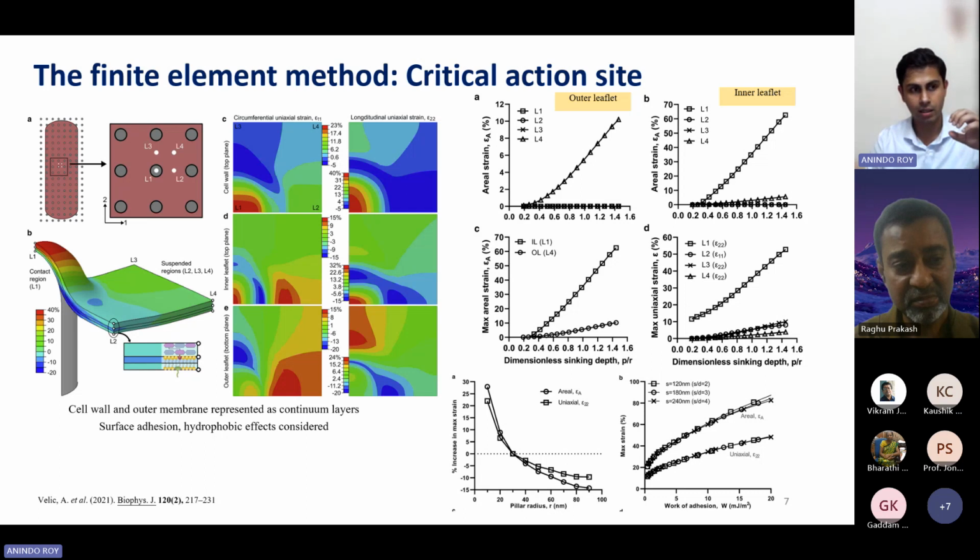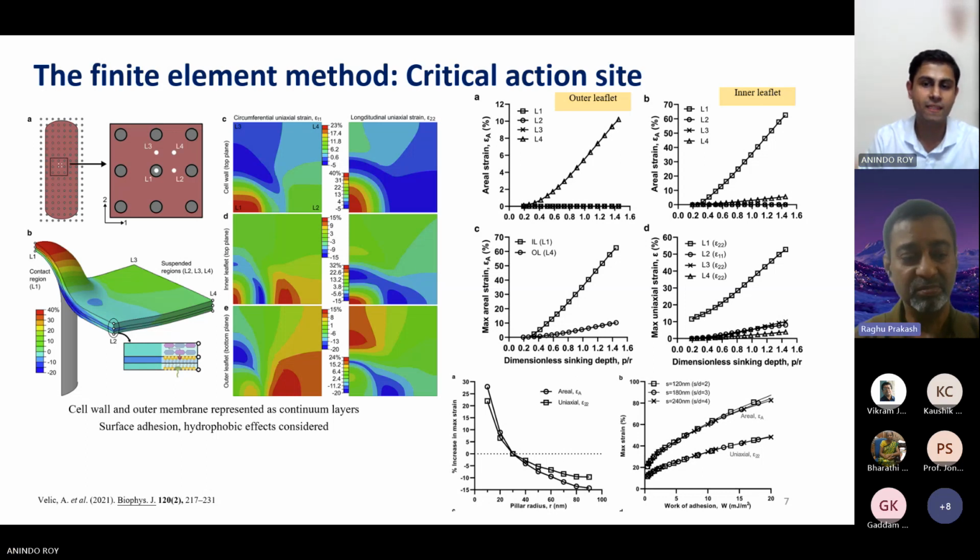For example, you can take a single bacterial cell and then take a capillary tube and create suction on the cell wall surface, and from that you can calculate various material properties. Similarly, you can take an AFM tip, poke a bacterial cell that has attached to a surface, and then from the force displacement curves, via some analysis, you can calculate different material properties. These studies have been done previously in the 2000s and the 2010s. We use those parameters. Good.